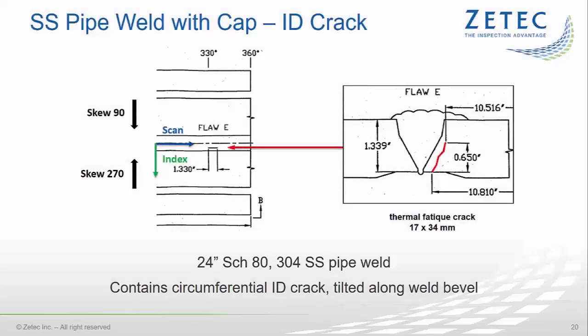Our second test case is a 304 stainless steel pipe weld, 24 inches in diameter and with a wall thickness of 1.35 inch or 35 millimeters. The weld has a double V-bevel and the weld cap is in place. We will use a large circumferential ID crack in the heat-affected zone of this weld to illustrate the difference in detection capability between the commonly used shear wave inspection techniques and the DMA probes generating L waves.